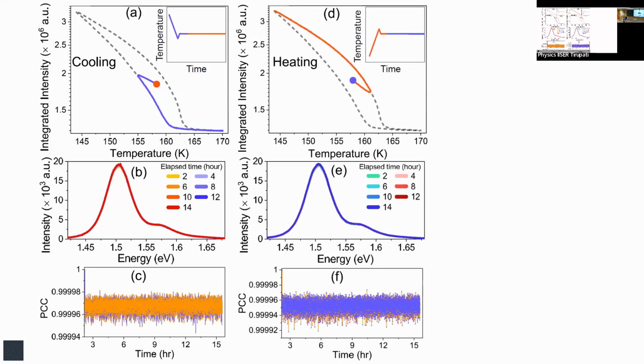In fact, if I plot this Pearson correlation function, you can see that it's 1 within an error of 10 to the power minus 5. It holds on to that particular optical signal as long as the temperature is held, exactly forever. It remains identical, so you can see that it doesn't vary, which is wonderful. I can do that either that way, or I can do the reverse. I start from the low temperature, heat up, come here, then down, go there, and I hold it there, and it remains there forever. You can see thousands of spectra taken, and it's all within an accuracy of 10 to the power minus 5 of being identical with each other.